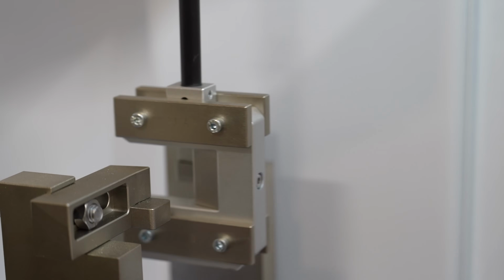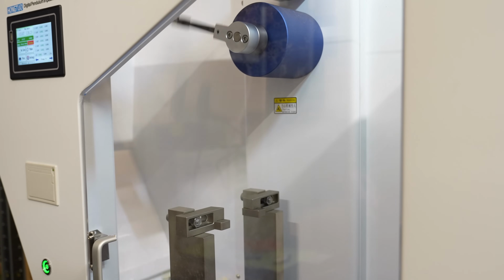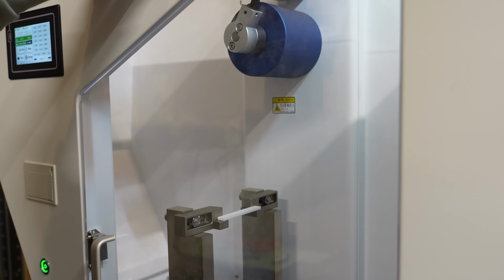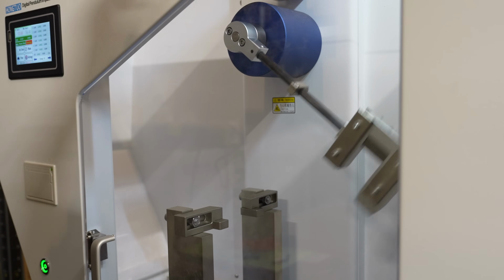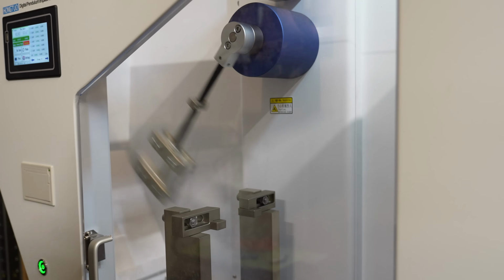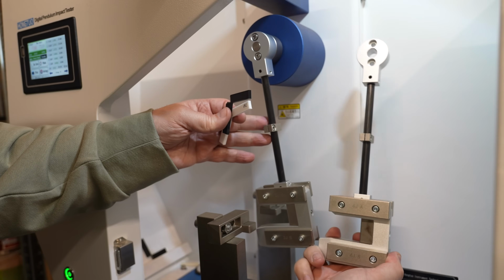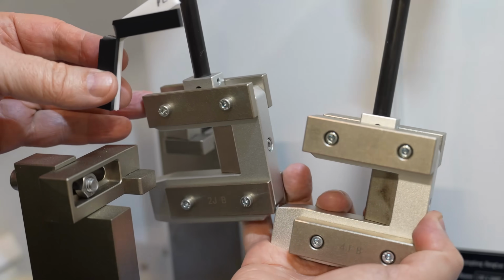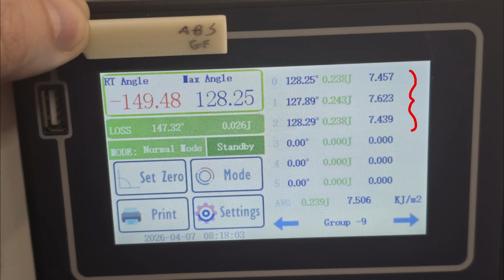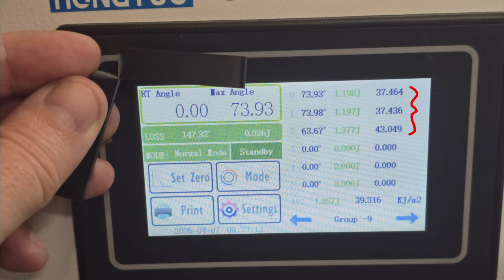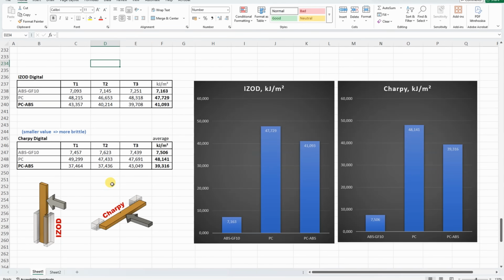Moving to the Charpy hammer, ABS-GF. PC, will it break? PC ABS. I was ready to move to the stronger hammer, but this was just enough. And the results, ABS-GF, PC, PC ABS. These are two different types of tests, but the ratio is very similar, so PC and PC ABS are very tough materials. ABS-GF looks brittle, but this is still tougher compared to the average PLA or PETG.